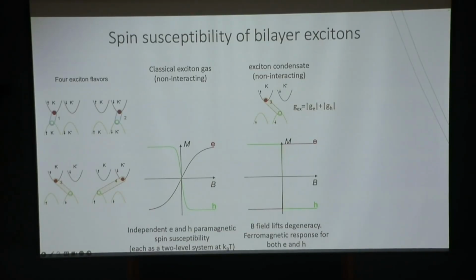And the fascinating thing about a boson condensate is that even a tiny energy difference will lead all the excitons to condense in that specific state. As a result, an infinitely small magnetic field will completely polarize the excitons, forming basically a one-component exciton condensate, and it will be effectively ferromagnetic. The smallest magnetic field will polarize it, and then electron and hole also get polarized at the same time.